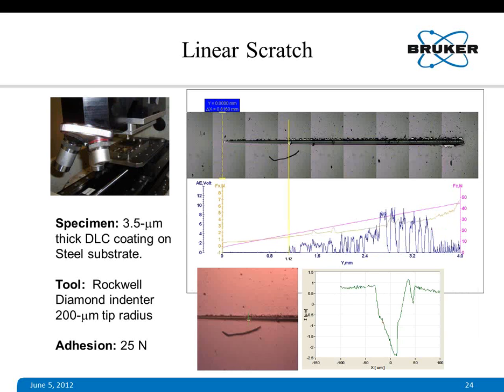Another example where we added an acoustic emission probe. And you see this is again a 3.5 micron thick DLC coating on a steel substrate.